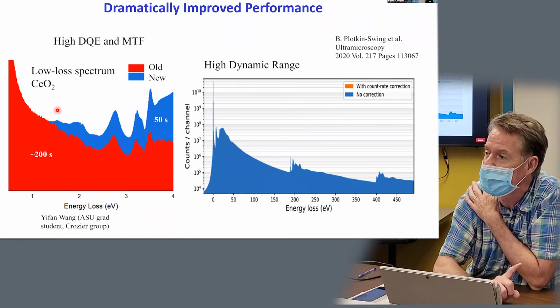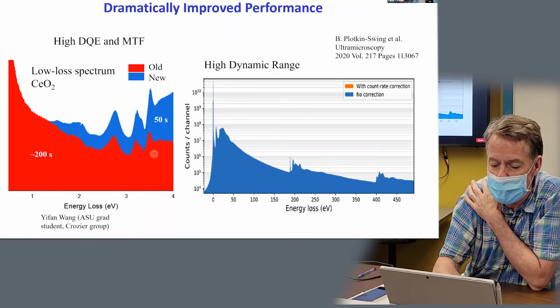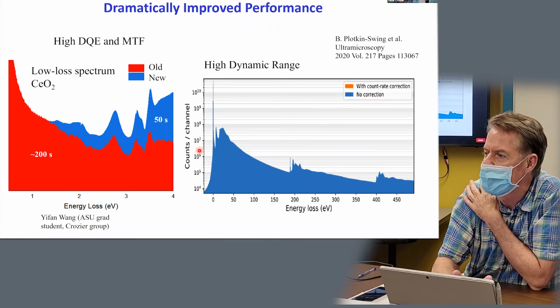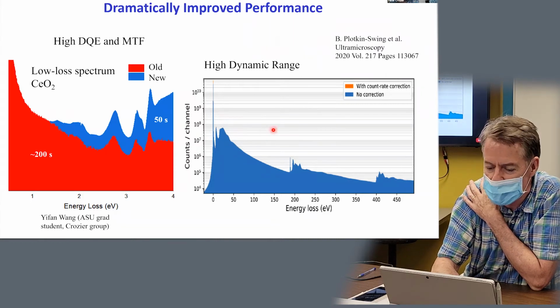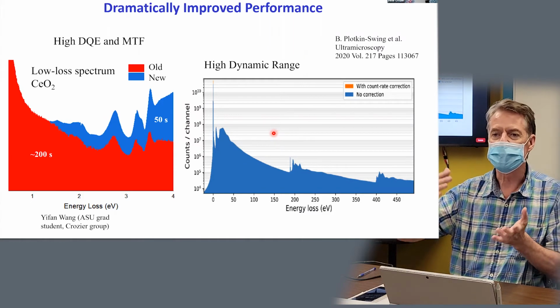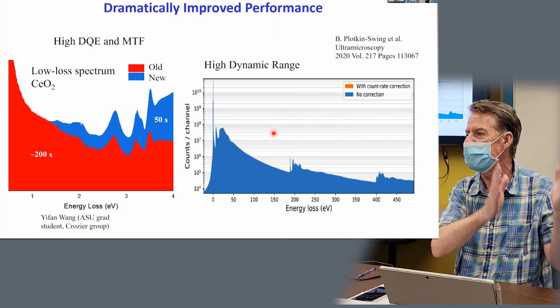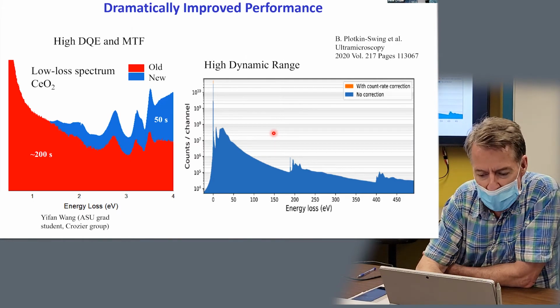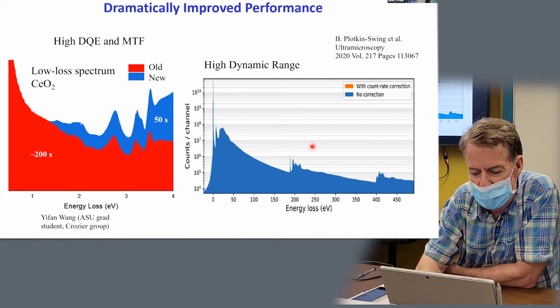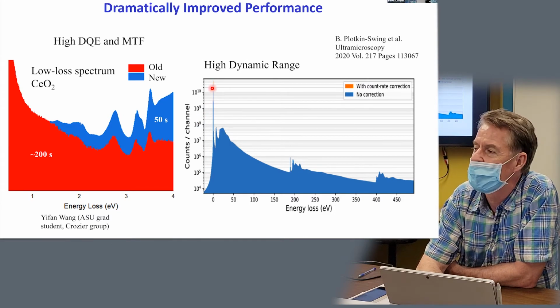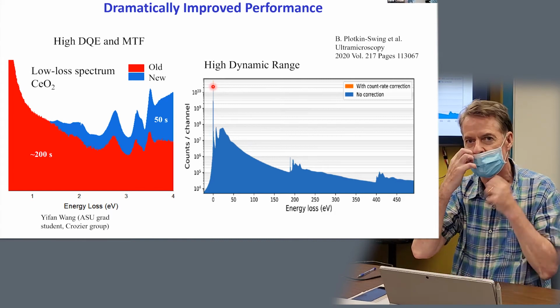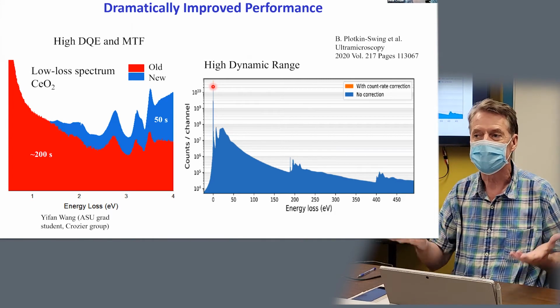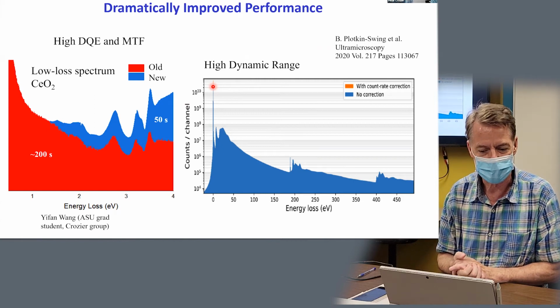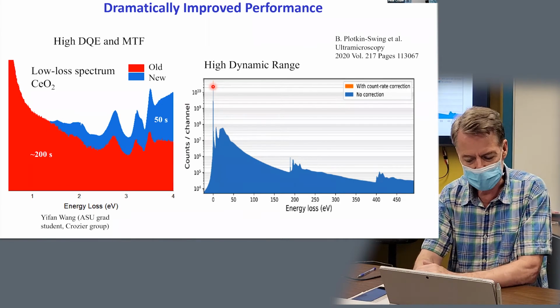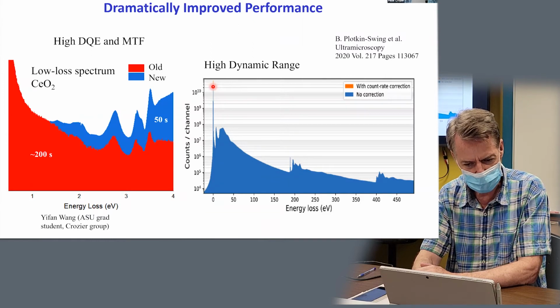The other thing about this detector, which is great, for those of you that know about spectroscopy, the electron energy loss spectrum typically spans about 7 orders of magnitude in terms of intensity. And usually most of our old detectors could only span 3 or 4 orders of magnitude. So we would have to record the spectrum in separate chunks. Now we can record the entire spectrum in one go and capture the entire dynamic range without any saturation effects at all. And again, for a lot of applications like elemental mapping, that's really going to be fabulous. So I'm going to hand you back to Shize, who will go through a few more examples.